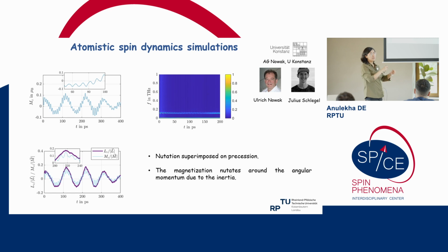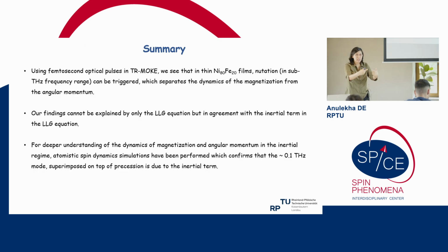When they simulated the system in the presence of this inertial term, they also saw high frequency oscillations on top of precession, and the frequency matches the experimentally observed values. In this figure, you can see how the magnetization initially nutates around the angular momentum, and on longer time scales, both become parallel and precess around the external magnetic field.